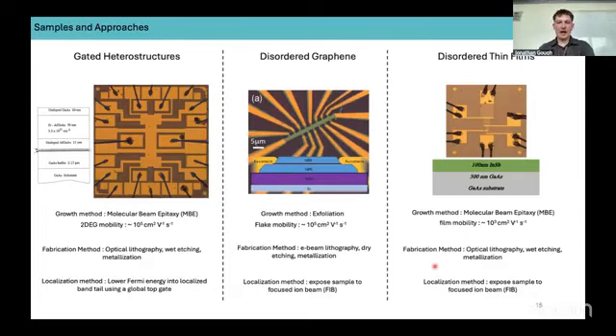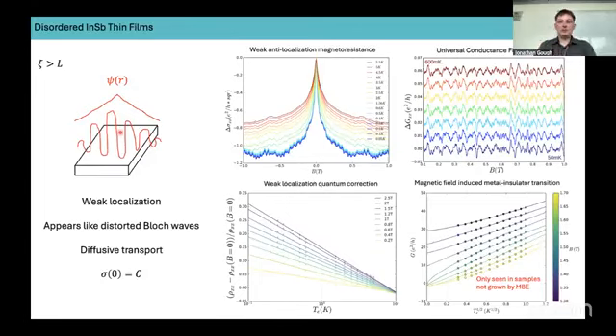And the wafers straight out of the growth chamber, so before we've introduced additional disorder, are already within this weakly localized regime. Disorder in these materials comes from two main sources: the interface roughness, so typically indium antimonide is grown on semi-insulating gallium arsenide, which has about a 12% lattice mismatch. This causes dislocations and interface roughness at the boundary between the indium antimonide and the gallium arsenide. There are also impurities from the growth chamber, which are essentially unavoidable. It shows up even when we change chamber types.